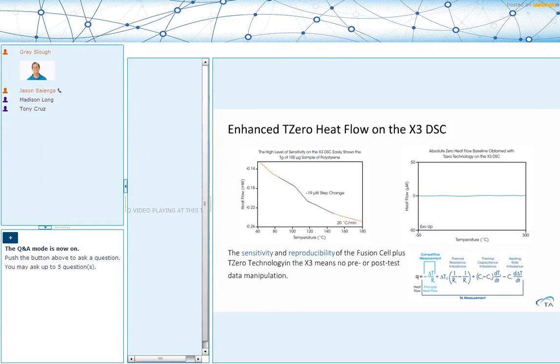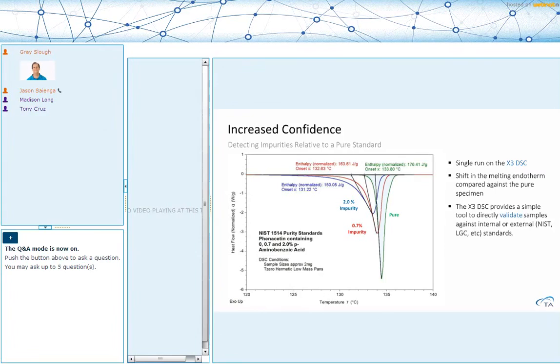The flat baselines, the reproducible baselines here in this example gives us the opportunity to see a small glass transition, a 19 microwatt step change of a 100 microgram sample of polystyrene. So without having this attention to detail on both the design and an understanding of the instrument impact, we wouldn't be able to confidently pull out a small glass transition like that in the polystyrene example. And so, really, the hardware design is built in a way that should provide a level of confidence and repeatability, and that allows us then the opportunity to explore our applications. It allows us an opportunity to see where the X3 provides benefit.